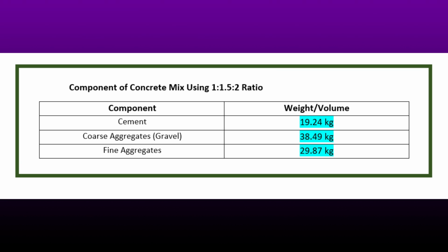After we calculated the volume of our mold and adding the volume of the other group's mold or samples, we found out that the cement we will be using is 19.24 kilograms and the coarse aggregates is 38.49 kilograms and the fine aggregates is 29.87 kilograms.